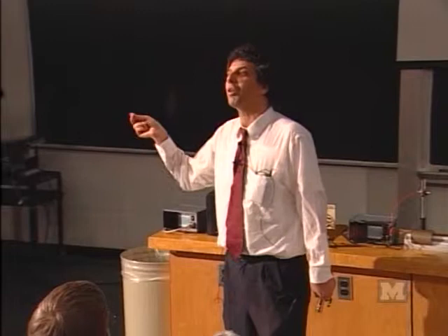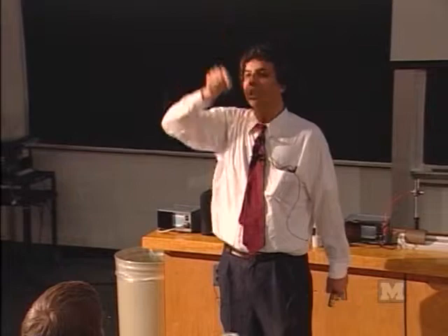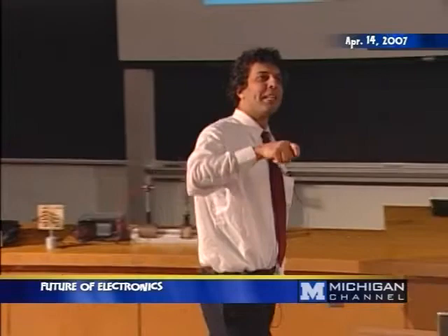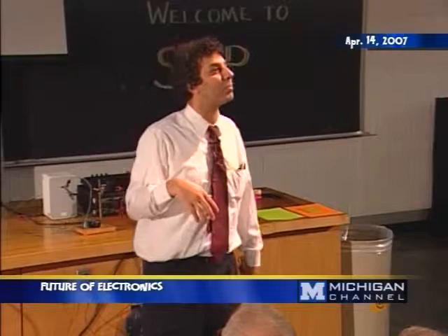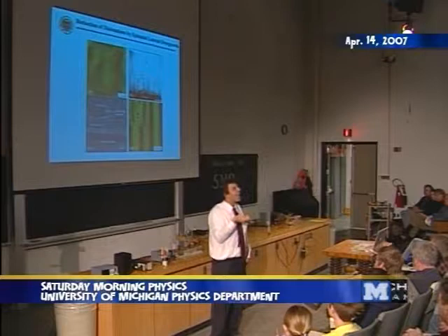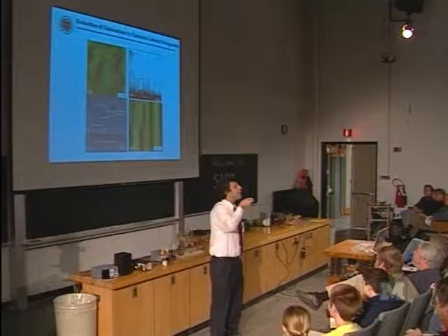Because if the material is pure, electrons and holes will recombine, and then they will generate light. If there is disorder of any sort, that's an alternative path, that's wasted power. So you can spin it around. Of course, when we talk to other gallium nitride people in the community, everyone knows it. But for a general audience, it is important. If you look at it in the big picture, a small gain in reducing disorder will imply better lights. And in the global sense, the impact is enormous.